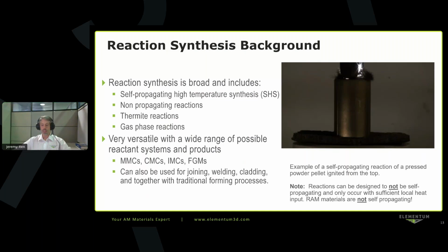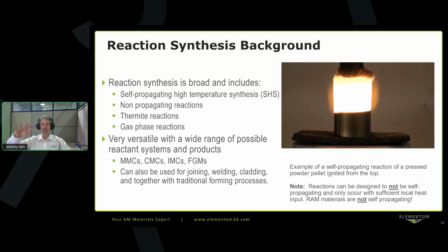I have a video here that's an example of a self-propagating reaction of a pressed powder pellet. So we took powder metals in the right composition, pressed them together, and then ignited it from the top. And you can see now, this is the ignition, and now the reaction has started. And in this case, it's a self-propagating reaction. The reaction releases energy that is sufficient to ignite the adjacent material, and it propagates in a wave-like fashion, very controlled in a downward fashion.